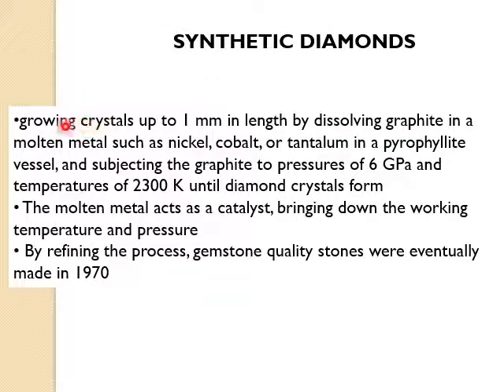Synthetic diamonds. How can synthetic diamonds be prepared by the high pressure method? By growing crystals up to 1 millimeter in length, dissolving graphite in a molten metal such as nickel, cobalt, or tantalum in a pyrophyllite vessel and subjecting the graphite to a pressure of 6 gigapascal and temperature 2300 Kelvin until diamond crystals form. So diamond is prepared from its other allotropic form, that is graphite, at very high temperature and very high pressure, 6 gigapascal.